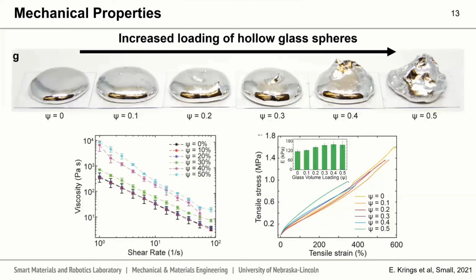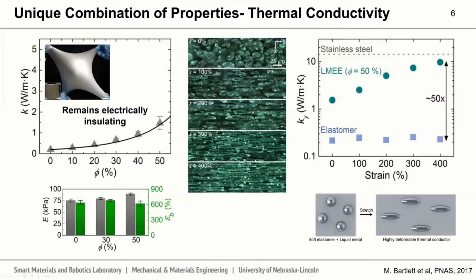Well, it looks like we do have a question from Susan Jansen. How does changing the aspect ratio of the liquid metal influence the strength of the material? Can you bias the mechanical performance? Yeah, that's a really great question. That's something we're studying right now that hasn't been studied in literature yet, understanding how the modulus of these materials changes as a function of its microstructure. Up to this point, we see very little changes, almost undetectable on some scales, and we are trying to understand if these changes in our modulus are a function of the printing and potential changes in chain alignment of the polymer, or actually a function of the microstructure of the liquid metal.